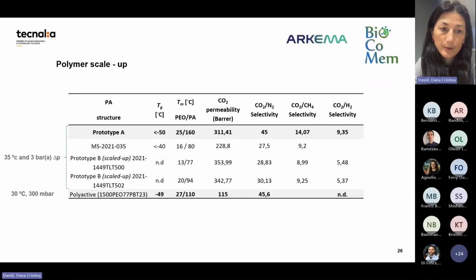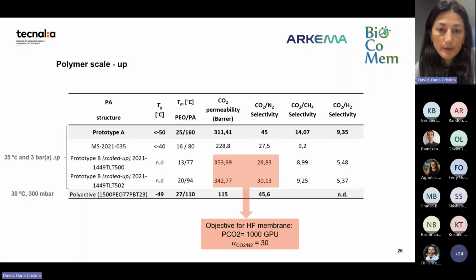Arkema did a scale up. Here I'm showing again the permeation results that were shown before by Katrin, the University of Maastricht. So there are two. We have this batch at lab scale, MS-2021-035, and then it was scaled up in two different polymers, with the only difference between them being a bit the polyamide to polyethylene oxide ratio, but it is the same chemistry. And with these ones, we started to make hollow fiber membranes.